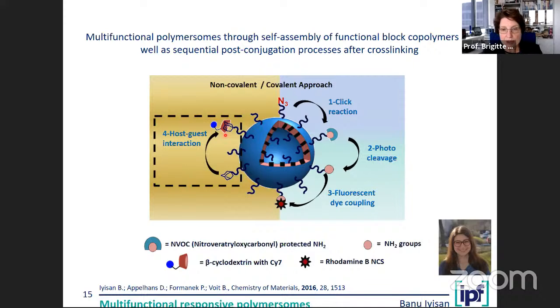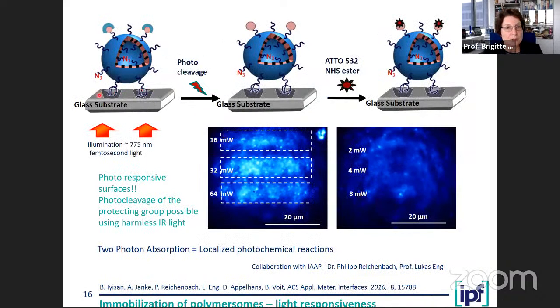And we have now established good routine work to even store our nanocapsules for a long time and reactivate them, and even ship them for several months, no problem. They are stable and reusable for various types of approaches. For example, we also put them onto surfaces by non-covalent bonding, having cyclodextrin and adamantane in a nice host-guest bonding, so they can stick to the surface. We can do irradiation of the photoprotecting group and then put some marker on it. It works well. You see here, when you have sufficient imaging with light of the right wavelengths, those nanocapsules light up, and it works very well, even in so-called 2-photon absorption regimes.